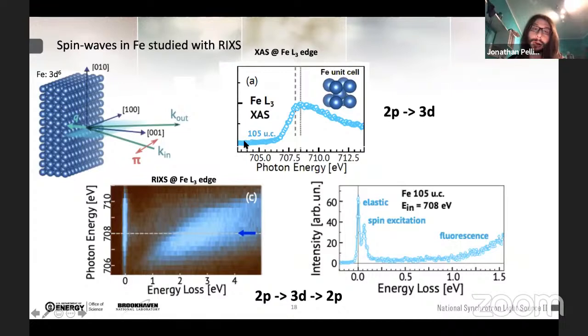So we collected X-ray absorption at the iron L edge, which is at an energy of about 708 electron volt. And we observed this pretty broad feature, which is normal for 3d transition metals. This transition, as I said before, is a transition from the 2p core level into the 3d level. Once you have done an X-ray absorption, the next step in a RIXS experiment is to start collecting spectra as a function of energy loss at different incident energies.